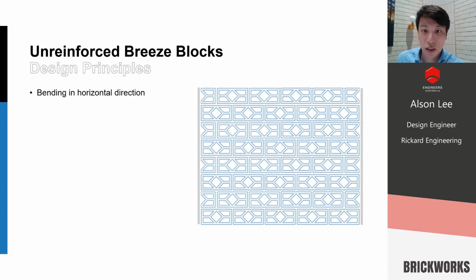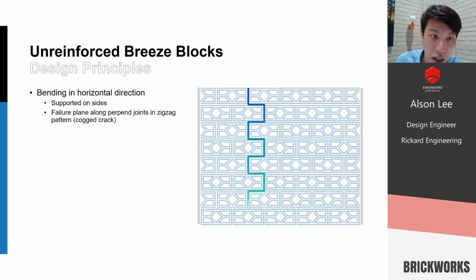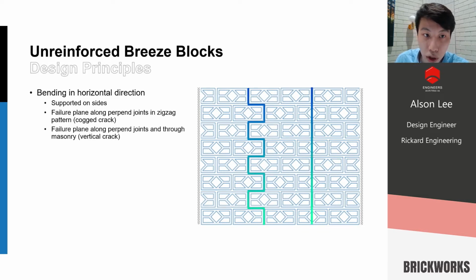Now when we're looking at the horizontal direction, with the wall supported on either side, again in stretcher bond, the failure plane we expect is in a slightly different manner. The first one is what we call a zigzag pattern or a cogged crack. In the diagram, it is illustrated as not in the center. If you were to imagine the cog crack forming within the center of the wall, in the midspan, this one's just for demonstration purposes, it is failing along the mortar joints. The mortar bed joints, which are the horizontal ones, and the mortar perpends, which are the vertical joints. In some cases, which is especially more pronounced in the breeze blocks, there is a failure plane along the perpend joints and also through the masonry. It's kind of like a straight crack through the whole wall. This failure is dependent on both the mortar and the block strength itself.